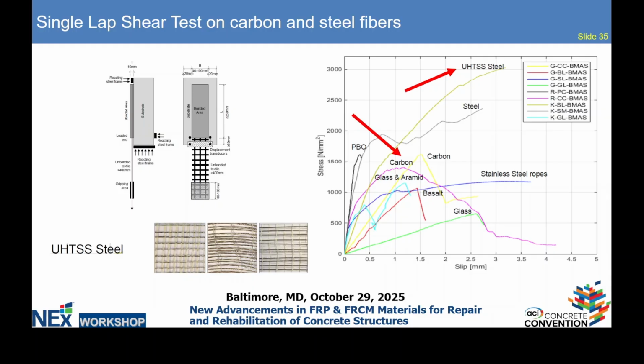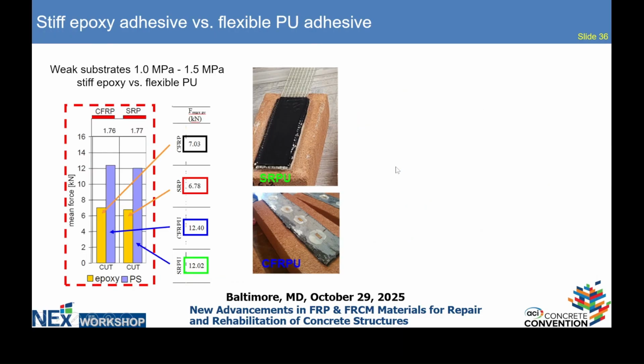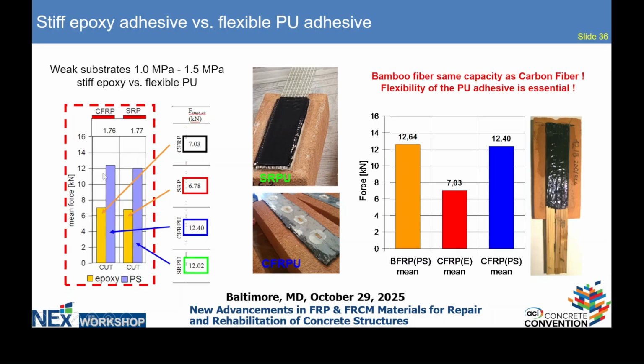So I will skip the introduction according to single lap shear test because Cristiano presented it very effectively. I will present two composite fibers, I mean ultra strength fibers from steel and carbon fibers. There are single lap shear test results. In yellow, you have epoxy adhesives. One is with polyurethane, one is with carbon, another one is with steel. So mean value is about 7 kilonewtons. When we applied polyurethane adhesive in the same system, you can see 12. But what is very tricky, when we replace in the same system carbon fiber with bamboo fiber, with grass, we also receive 12 kilonewtons.